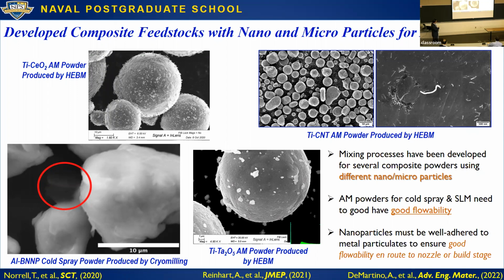And what we've done is we've essentially decorated them with oxide particles, in this case tantalum pentoxide. And you get very uniform distribution, right? You see essentially no agglomeration. So you're really trying to get two things.